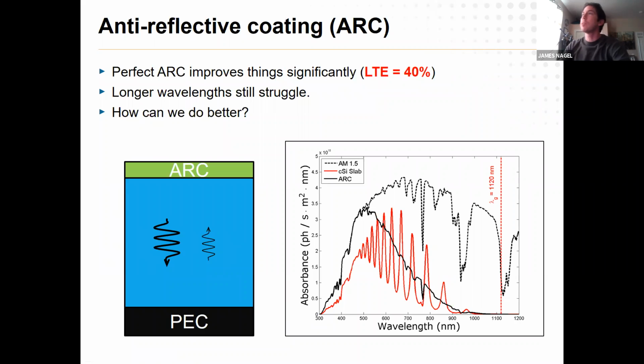So the first step is you want to add an anti-reflective coating. Usually silicon nitride will do that. And in this case, we're doing a completely idealized model. Okay? So it's not even a real material. So it's perfect anti-reflection at all frequencies. So you see how it smoothed out all of those resonances, because what you're seeing is light comes in, propagates down, strikes the back contact, comes back up and leaves out the top again.